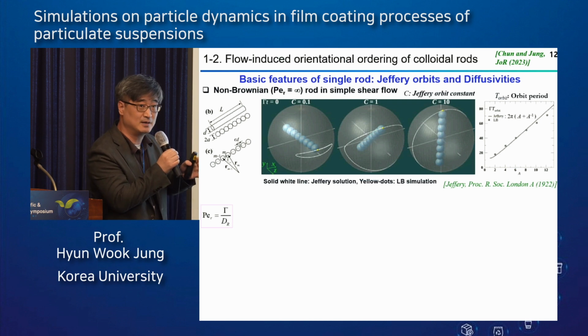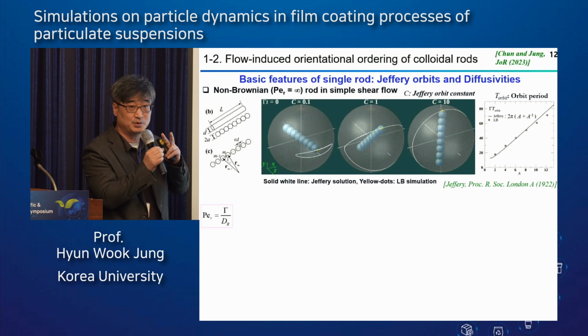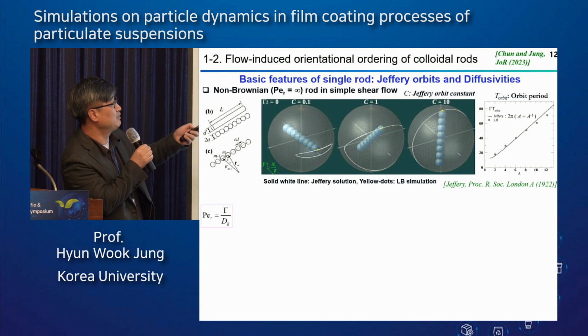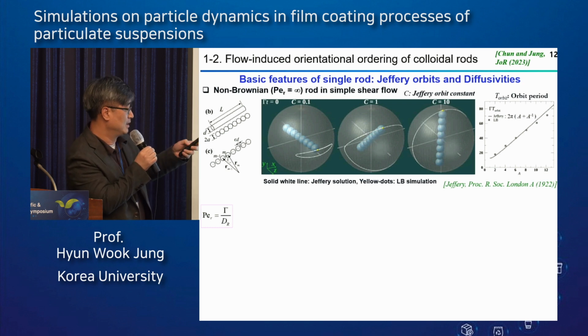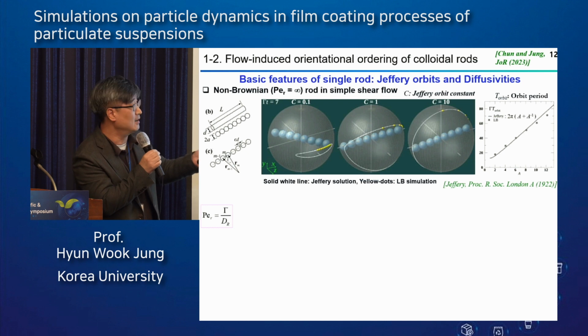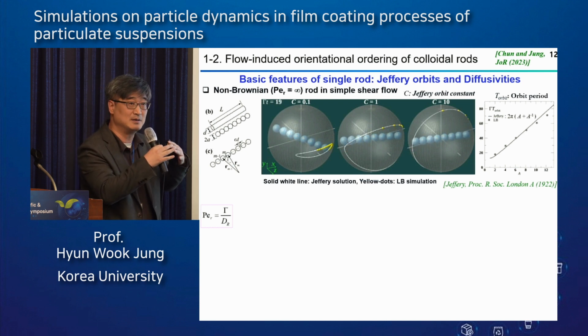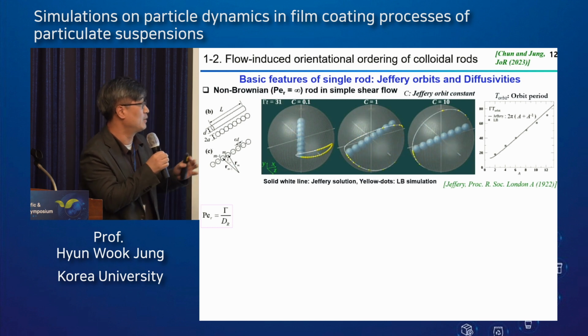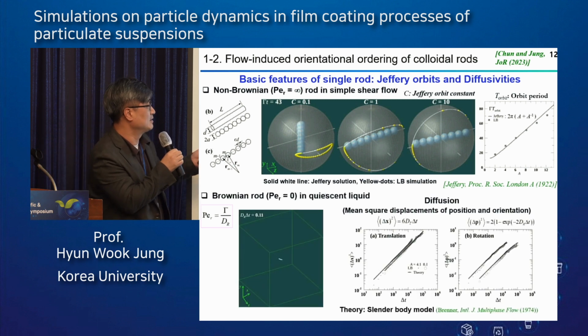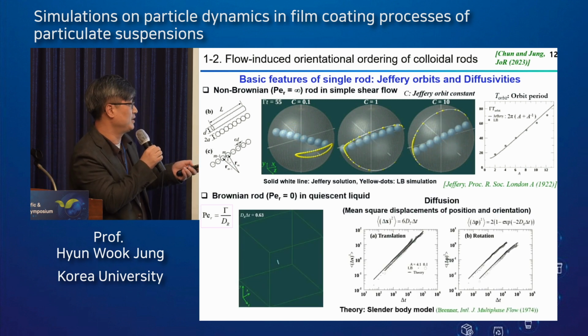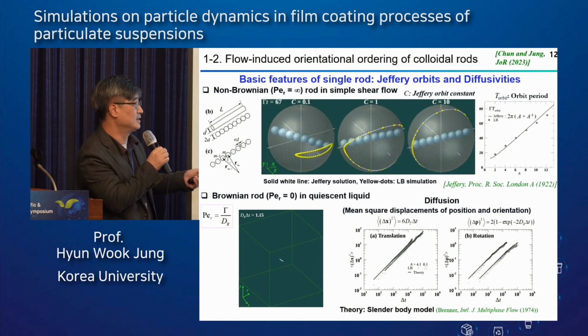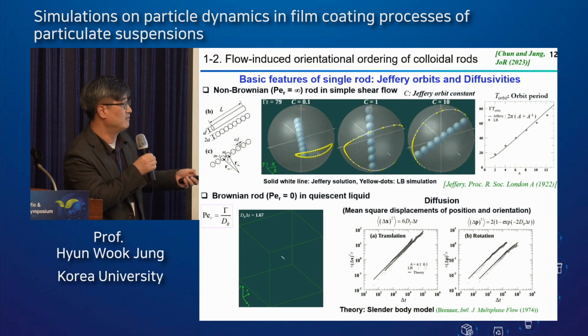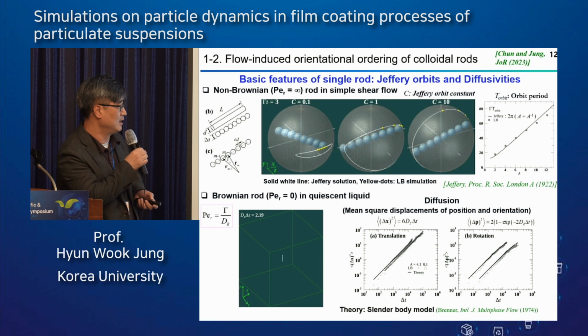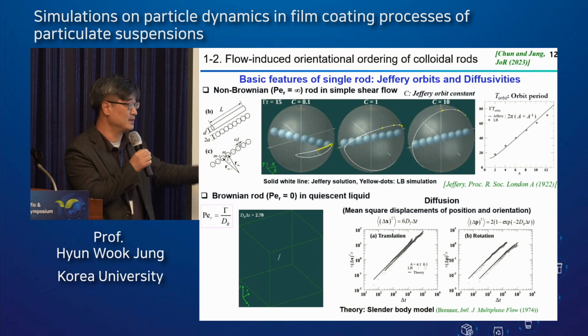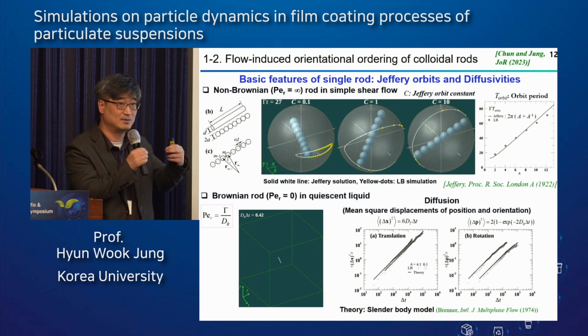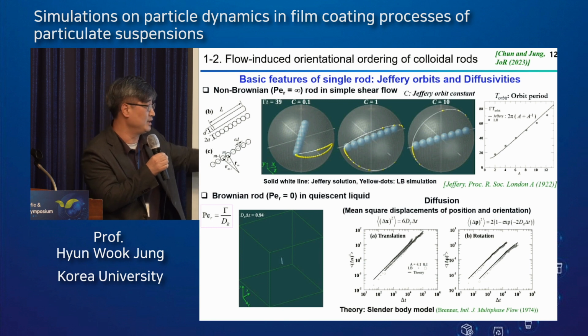In that case, we first checked the basic features of the rigid rod in two cases. The non-Brownian rod in simple shear flow at the high Peclet number regime will show a Jeffery orbit, which is a very classical movement of a rigid rod in simple shear flow. So exactly correct. Good agreement. And in the second case, for the Brownian rod at Peclet number 0 in a quiescent liquid, we compared the mean square displacement of a single rod in position and orientation data, as shown here, giving good agreement between the LBM simulation and the slender body theory model. That is a classic model for the Brownian rod in a quiescent liquid.